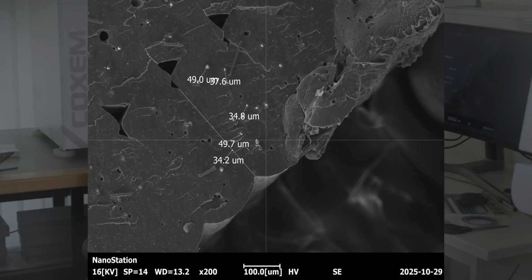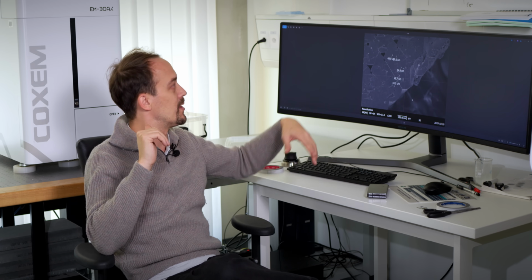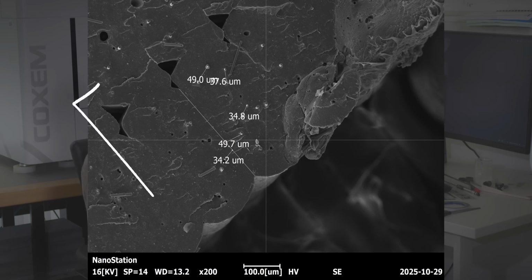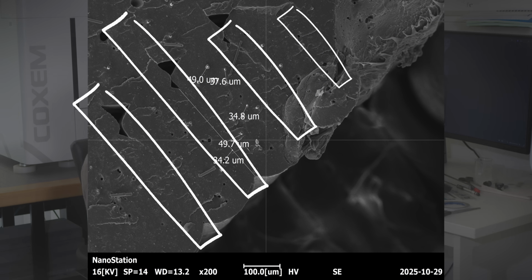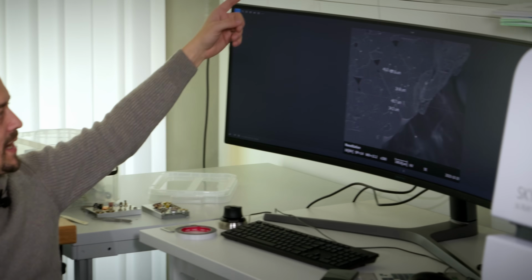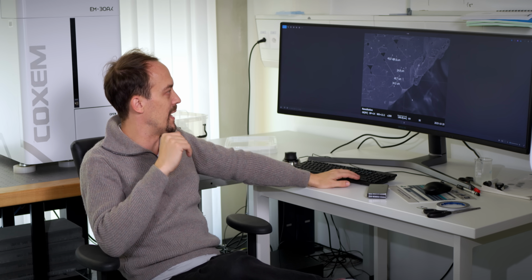That means that in the layer area, the distance between one carbon fiber and the other is about double that, so about 100 microns. So that means it's not just pure coincidence or dumb luck that we focused on an area where you have no carbon fiber in between, because I looked through a lot of areas of this whole thing. And as you can see here and there and there and there, nowhere is carbon fiber in between layer lines. Of course, you have this one laying down there, but this is just after breaking. I basically bent it a little bit.